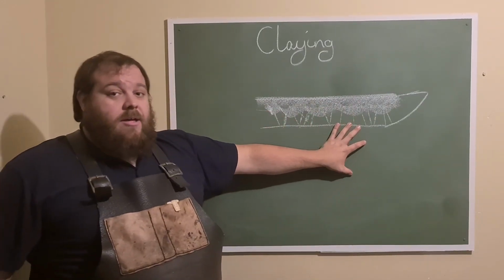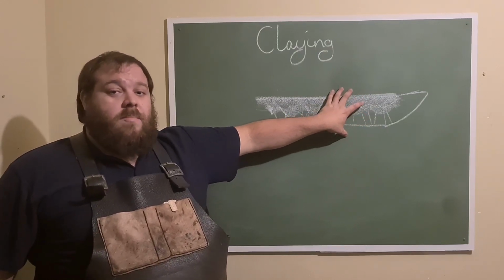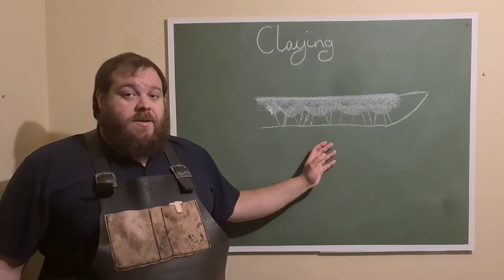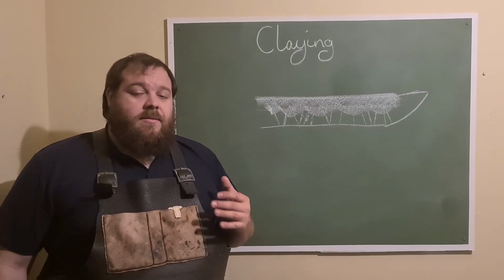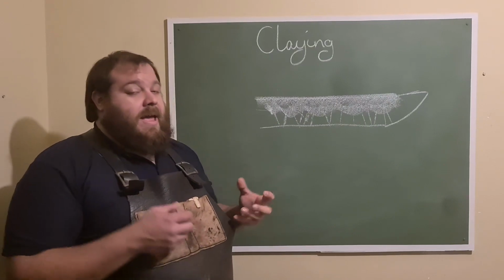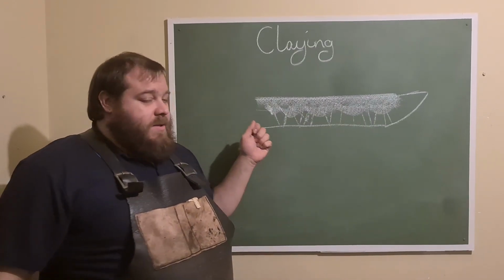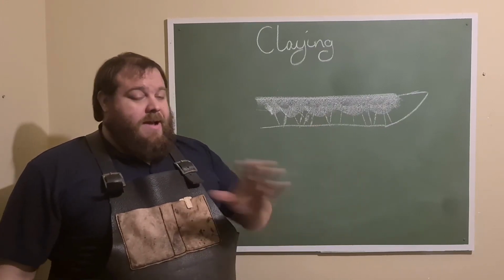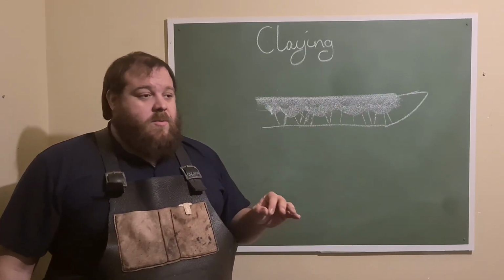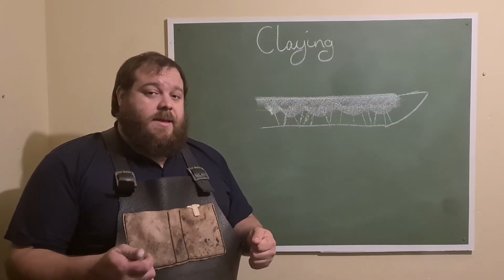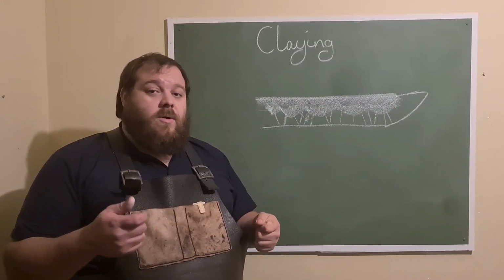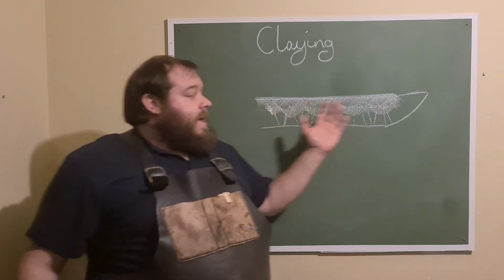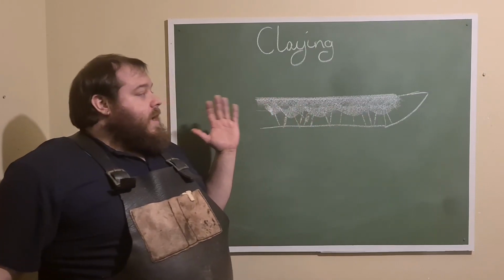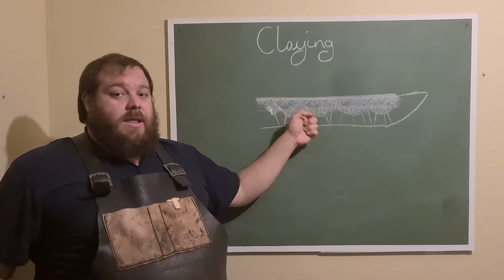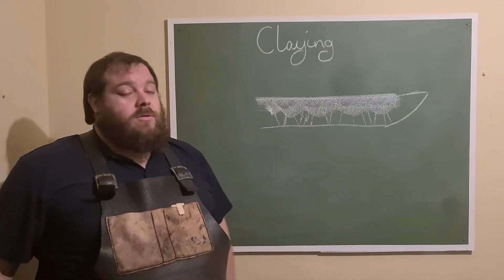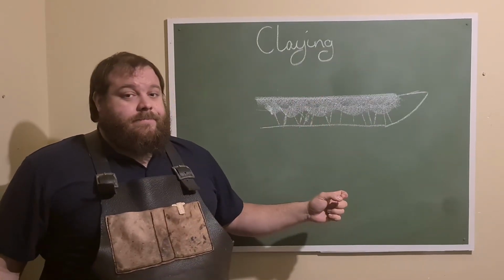One thing that I've found really helps with applying clay to a blade is to apply a layer of slip first. Now, slip is purely a thin amount of clay. So it is just clay with lots and lots of water, very basically one grain of clay thick, plastered on the thing. You want to degrease incredibly well, and then I normally rub the blade with the slip, and that actually cleans off any other oils that you might have. You'll then let that very, very thin layer of clay dry over the whole lot, and that's when you apply your clay to the spine and to your ashi, and that will help it all adhere.